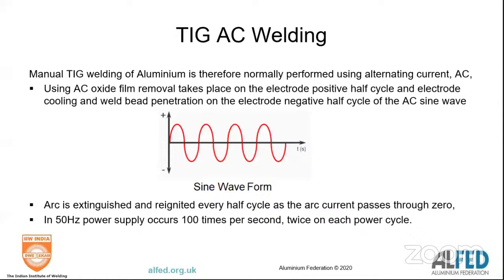Most TIG, for the reason of the problem of heating the electrode and breaking off the oxide, most TIG in the UK is AC welded or square wave welded. So in essence, in the positive cycle, you're breaking off the oxide. In the negative, you're welding and keeping the electrode cool.